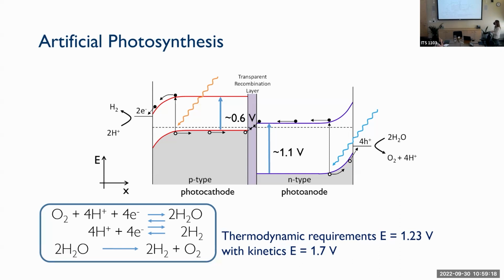The energy that is involved in this, specifically for water oxidation, is thermodynamically 1.23 volts. But then you have the kinetics that are related to the semi-reduction and the semi-oxidation reactions. And this takes the energy that you need for the process to about 1.7 volts. It means that you need 1.7 volts to autonomously split water. You either get it by plugging into the wall, or by having the right choice of materials, shining light on them, and getting that energy, just like with the sun.